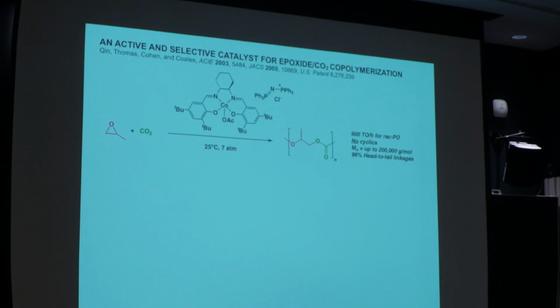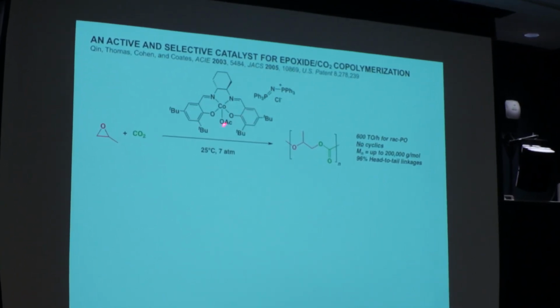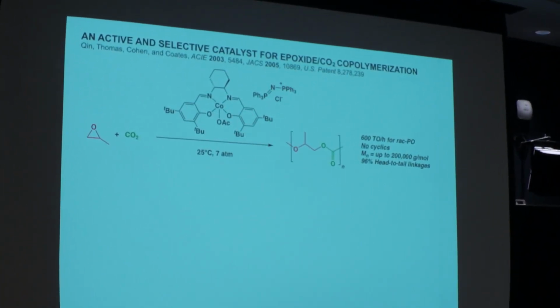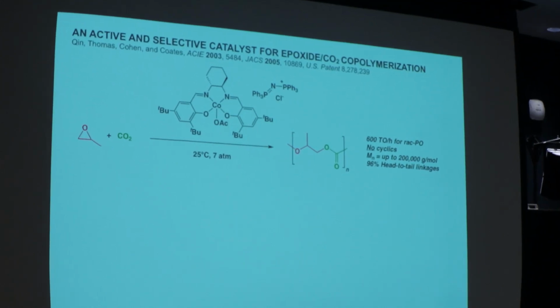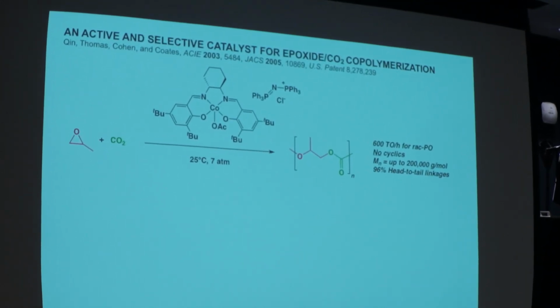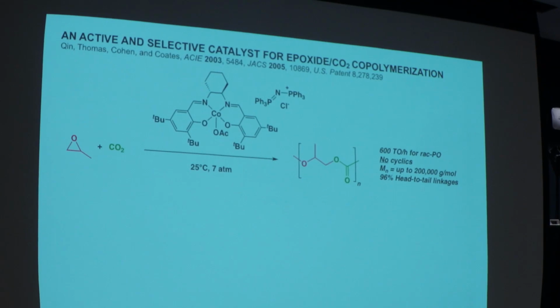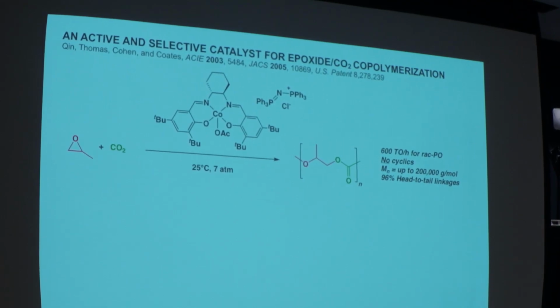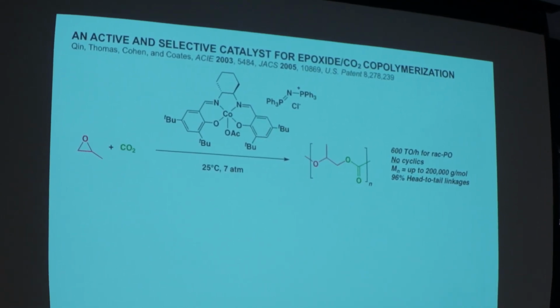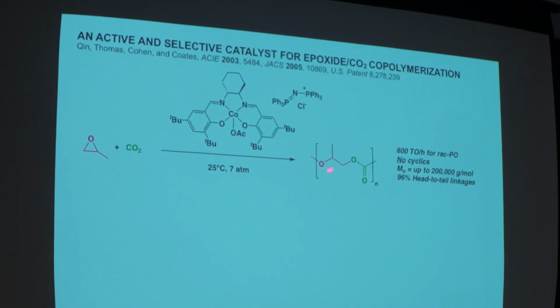The catalyst that we developed is based on a cobalt salen. It's activated by an ionic species. These are interesting catalysts because they work at very low pressures. You can actually put a balloon of CO2 on the top. You don't have to use really high pressures of carbon dioxide. The polymerization is very clean.